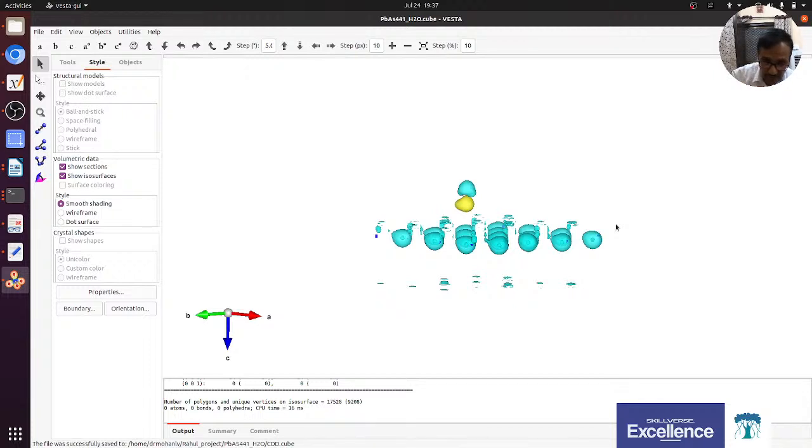And this type of output, especially that lower part and other part, is because of the selection of the lattice parameter. So just avoid that vacuum created, because I have created 10 angstrom vacuum. That's why it is trying to link with the neighboring one. So this is looking good, no problem.